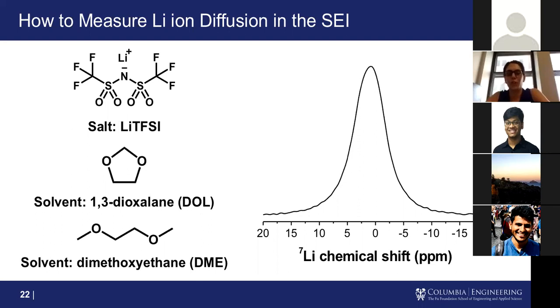But we know from our solid state NMR that we likely have lithium fluoride, we have lithium near organic species, and lithium metal always has an oxide layer on it. So we need to come up with some way to deconvolute this peak to assign all those individual species. What we do in this experiment is we play a little game and we pass magnetization between different atoms. We can pass magnetization from our fluorines to our lithiums to see which region of this spectrum corresponds to lithium fluoride. We can pass magnetization from our protons to our lithiums to see which region is lithiums near the organic components. And we can also just assign, where does lithium oxide show up here?